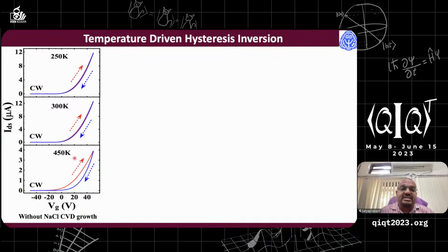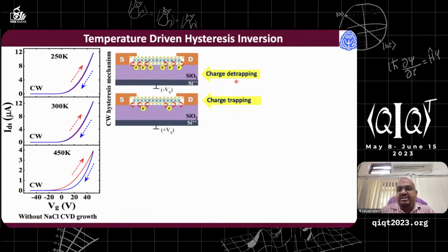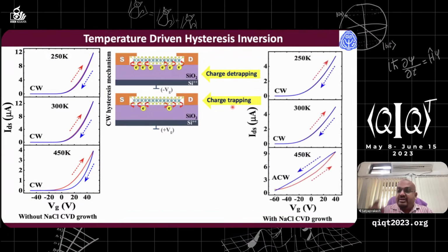But here we have grown this sample without NaCl, and you can see here, as you increase the temperature, say from 250 to 450, it is always a clockwise hysteresis. This is by considering the charge trapping and detrapping, which I'm not going to discuss in detail because of lack of time. But interesting things come into the picture when you compare this result with the sodium chloride assisted grown MoS2, and you can see here from 250 to 450, when you characterize this material, it shows a change in the hysteresis.